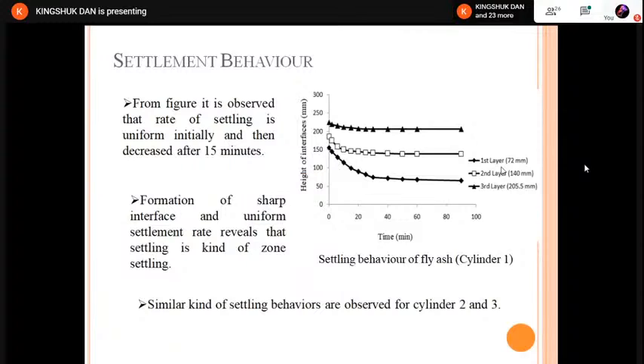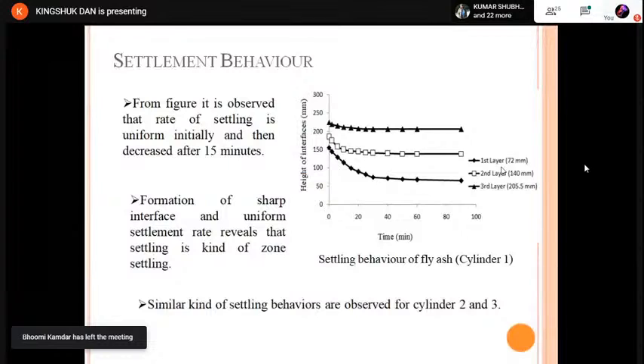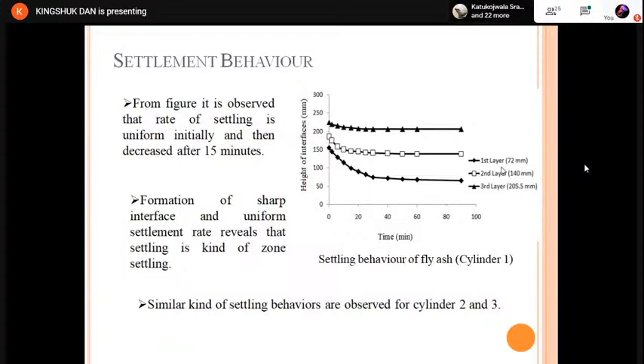This is the settlement behavior. You can see in the y-axis it is height of interface, and in the x-axis it is time. And this is for cylinder 1. Initially settlement is uniform, but after 15 minutes the rate of settlement is reduced, and after 30 minutes settlement is already asymptotic, and it is clearly seen here. Okay, similar settlement behavior is observed in cylinder 2 and cylinder 3.